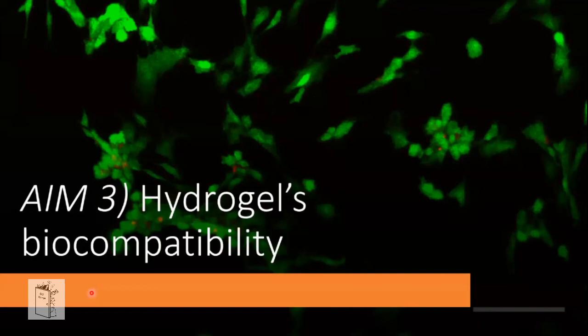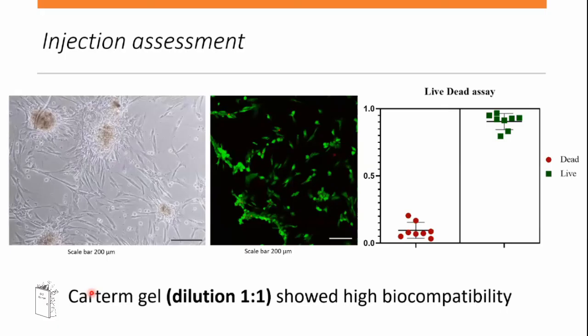Finally, we investigated the biocompatibility of the hydrogel using a live/dead assay. The CARTERM 1:1 dilution showed approximately 90% viability with a standard deviation of ±5% — a result we were very happy with. The gel was both biocompatible and injectable. Microscopy also showed micelle formation with cells aggregating and spreading, finding their own way — promising preliminary results.